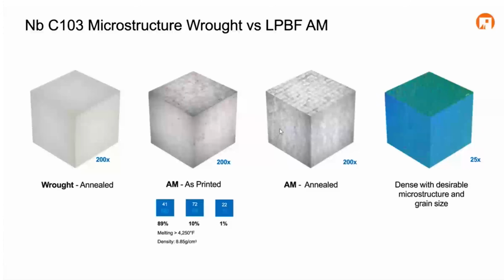But you can see clearly, we have a little bit of propensity for grain growth across the layers, and you can see clearly the weld tracks here. So we're talking about weld pools that are 175, 225 micron-ish wide, and about the same in depth.